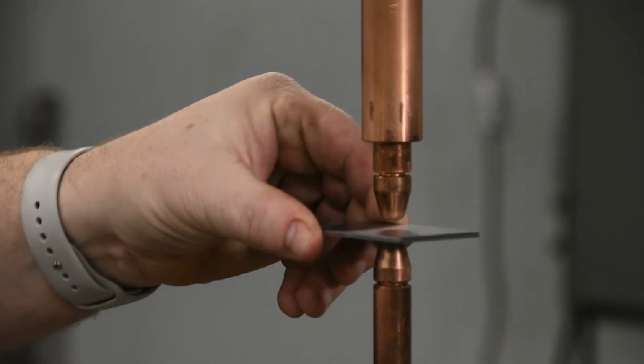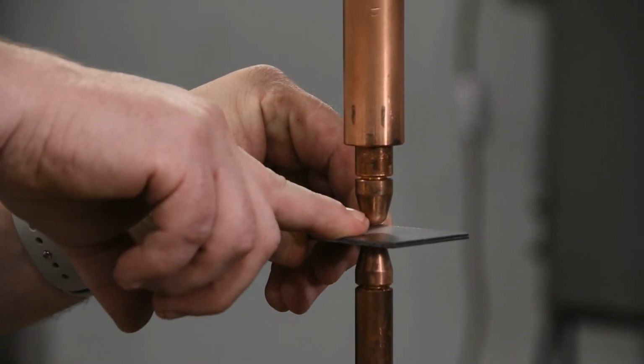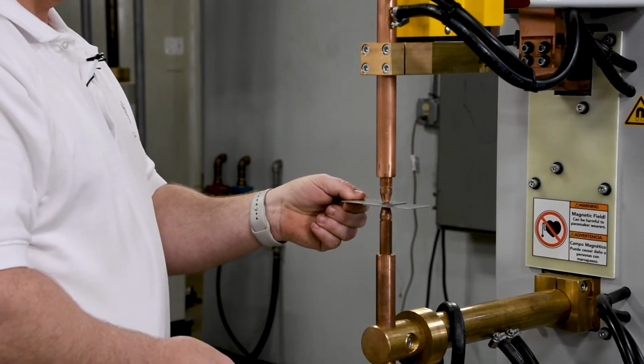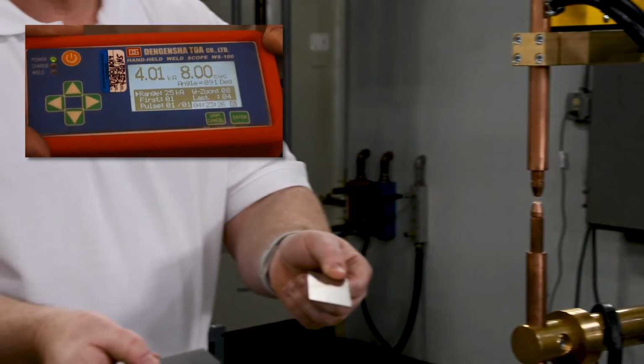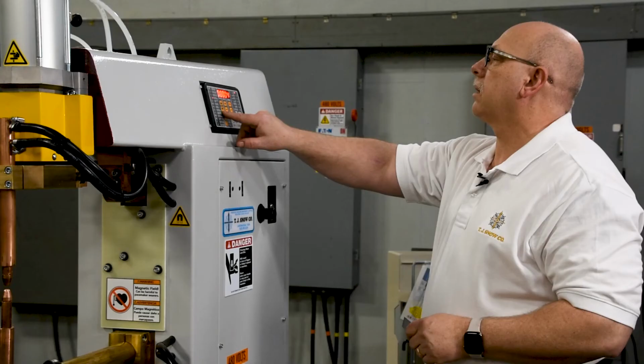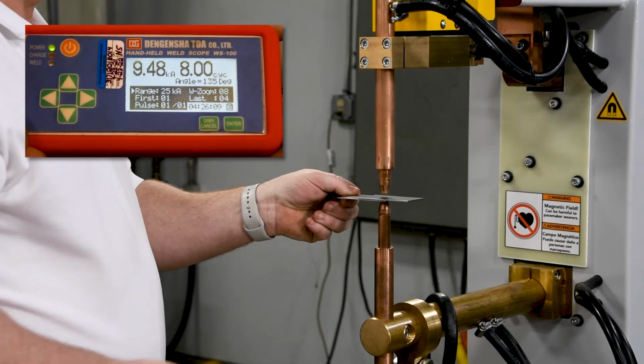Now, place the controller in the weld mode and ensure water is circulating. Place coupons or part between the electrodes. Where part geometry allows, there should be a quarter inch gap between the upper electrode and the material to reduce the pinch point risk. Initiate the machine and make the first weld. Observe the current reading on the weld scope. If the current is below the recommended value, increase the current in amps or percent until an appropriate current value is reached. If the recommended current value cannot be obtained, it may be necessary to increase the tap setting on the welding transformer to reach this value. Increase one tap position at a time and then re-weld.